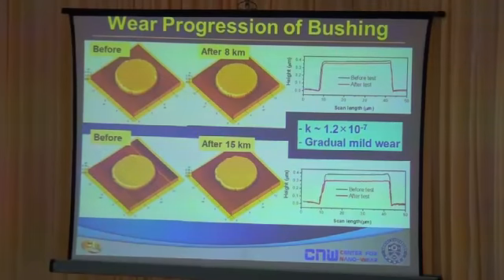Because as you know, if you use 2 flat surfaces in wear test, the biggest problem is with alignment. So in order to overcome the alignment, we don't apply external forces on the specimen. It's a natural weight that is being applied to the counter surface. And we run this bottom specimen very slowly so that we can maintain relative flat-on-flat contact. Now, the good thing about this kind of experiment is very simple, and we can run experiments for a very long time. Unlike the few millimeters that you use for the slide in AFMs, we run these experiments for kilometers.